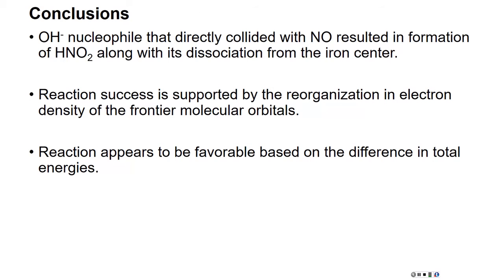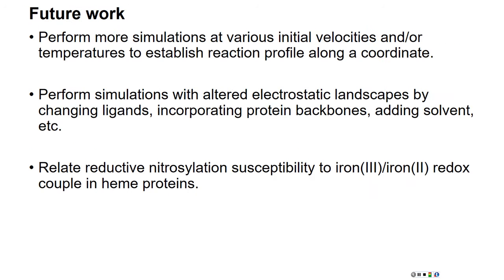All right, so in conclusion, the hydroxide nucleophile here, when it directly collides with the NO, does proceed with the reaction. This is supported by the reorganization of the electronics between where it did not undergo reaction and where it did. And one could state that the reaction appears to be thermodynamically favorable, but that may be an artifact in how the simulation was run. There's plenty of future work one could do with this from a kinetic or thermodynamic standpoint. But one would like to relate reductive nitrosylation susceptibility to the iron(III)/iron(II) redox of, say, proteins.